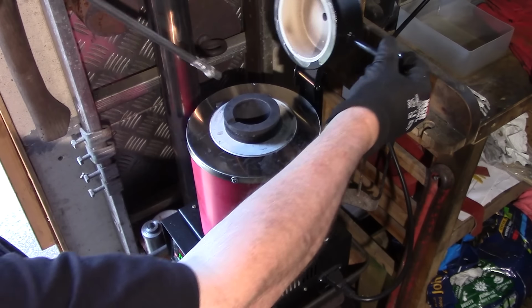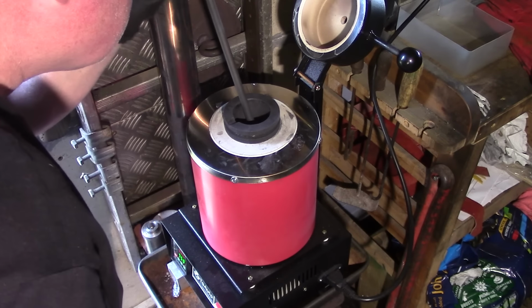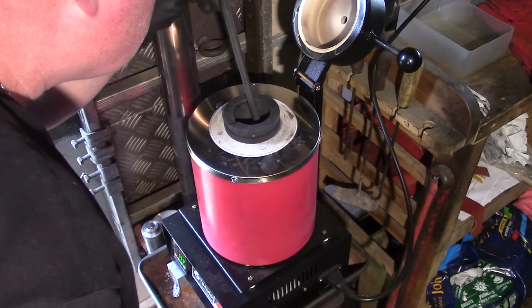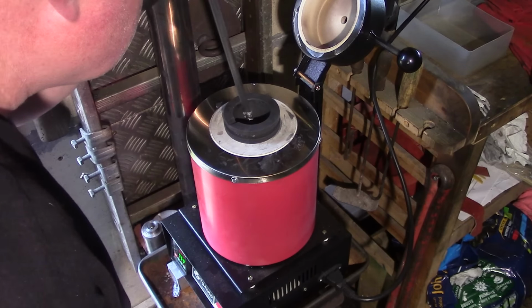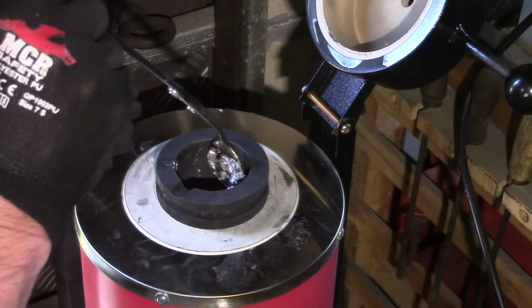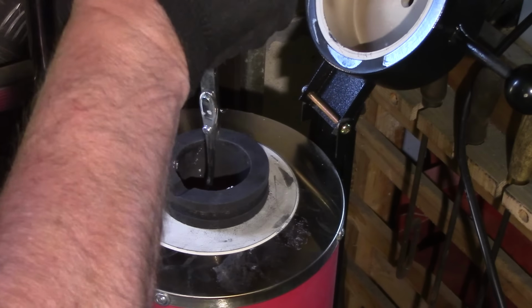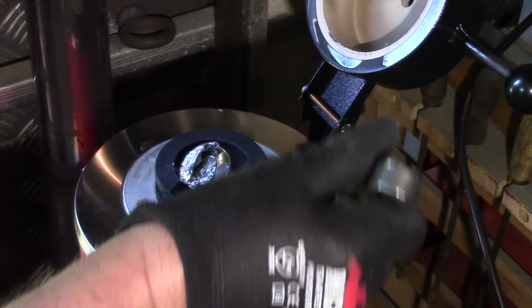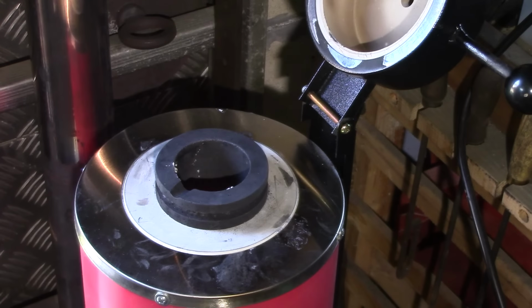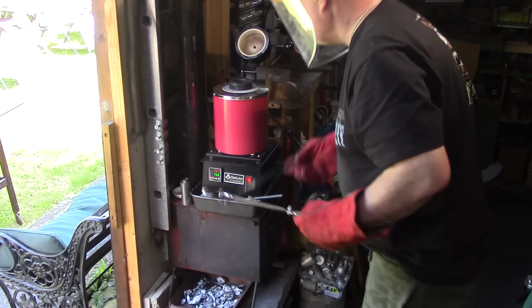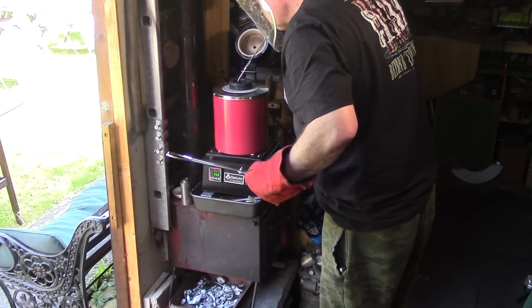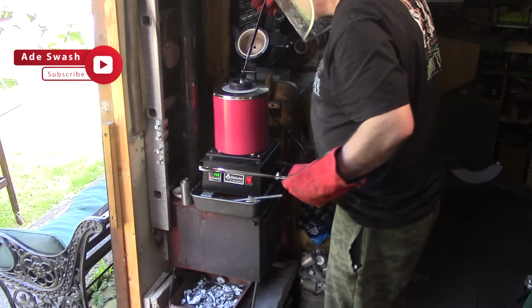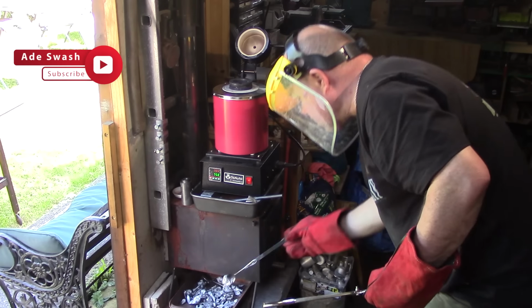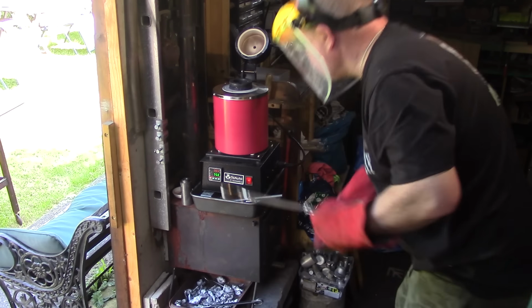After about 20 minutes, the entire quantity of metal is now a liquid, and a gentle stir with a graphite rod ensures that there are no solid metal pieces under the liquid surface. The top surface of the molten metal will have some oxidisation, and this is scraped up with a spoon and discarded, leaving a shiny top to the metal. Then, with my full safety gear on, I can now lift the crucible out and make the pour.